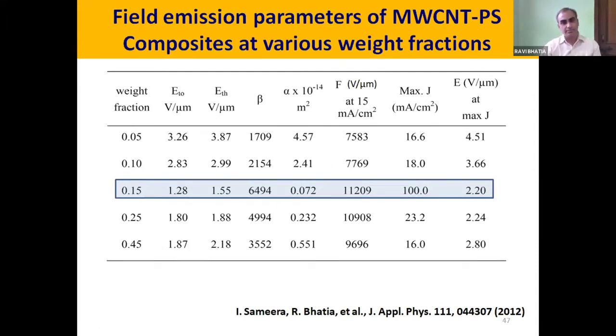theoretical models which can give us the optimized number of protrusions that can give rise to the highest field emission current are missing. So theoretically we are not able to explain this, but experimentally it is quite clear that because beta is more, beta meaning field enhancement factor, the applied field becomes a locally enhanced electric field. And there is one more important factor, that is the F value. It is even higher than the beta factor. So field emission from composites made up of CNTs can be one route for desirable field emission characteristics.